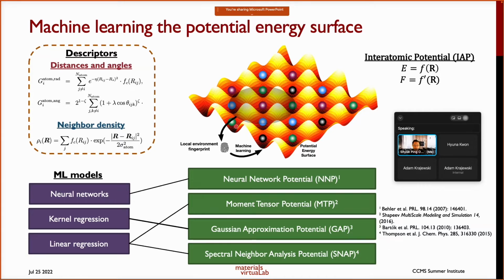any system, right? So the way that this works is basically you take the local environment around an atom, and you describe it using some local environment fingerprint. That local environment fingerprint can be things like the distances and angles between the atoms or the neighbor density around the atom. And you generate a fingerprint, and you use a machine learning model to map the local environment fingerprint to the potential energy surface, or rather the energies and forces on the atoms themselves.